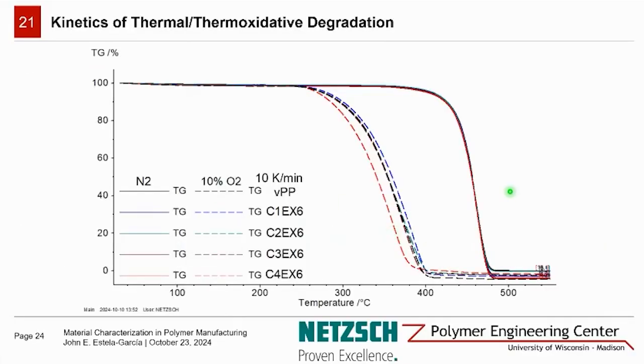In this slide here, we're observing the results of TGA of the virgin material compared to various final extrusion conditions, with respect to both nitrogen and an oxidative environment. So when we're comparing the results of the thermograms, we can see how the stability of the polymer is affected by the testing environment. For the inert condition, we appreciate that for all the samples, no matter if they've been extruded multiple times, regardless of their extrusion conditions, they demonstrate the same degradation behavior. We're just seeing one singular slope.